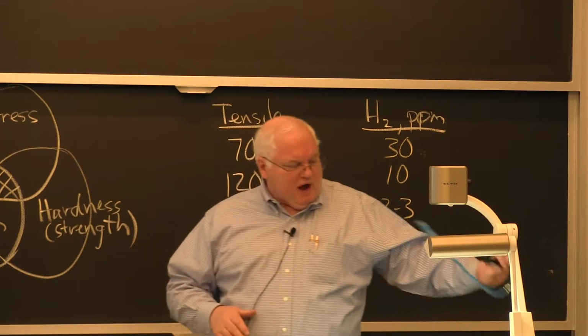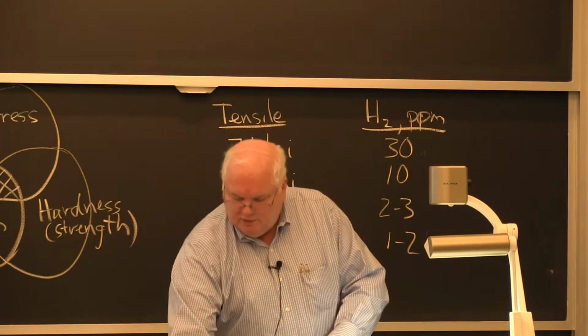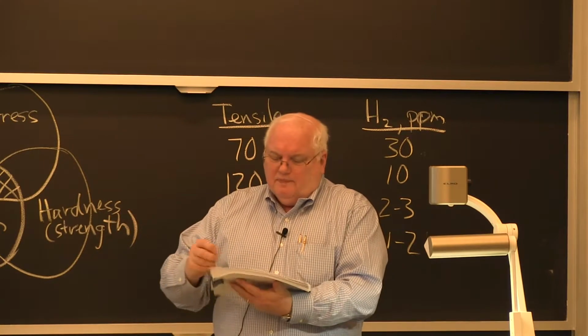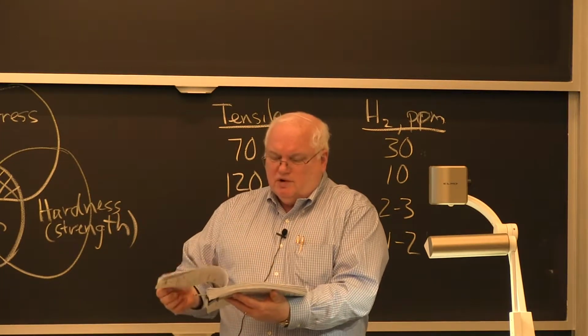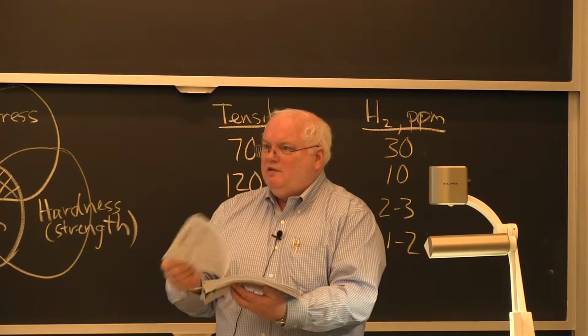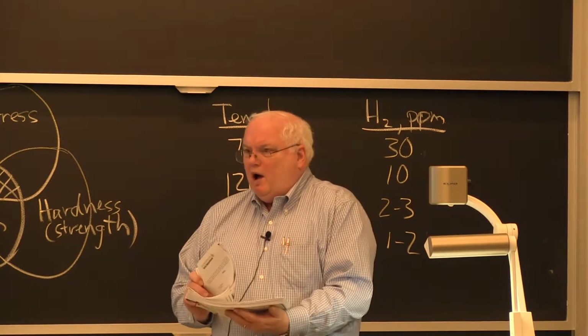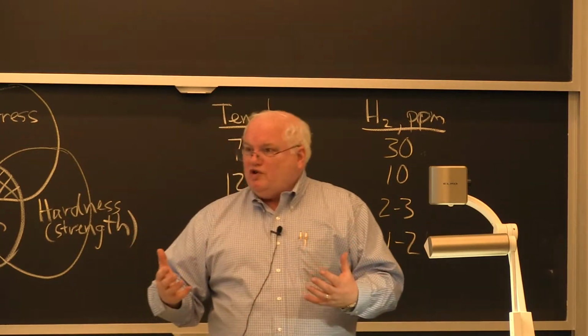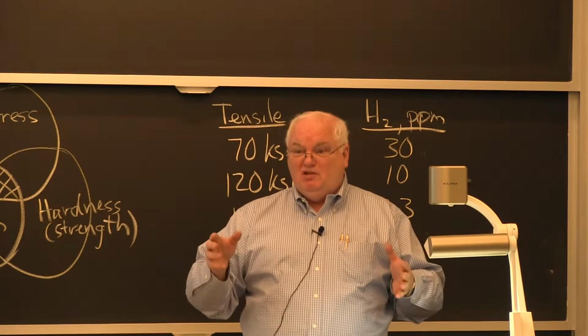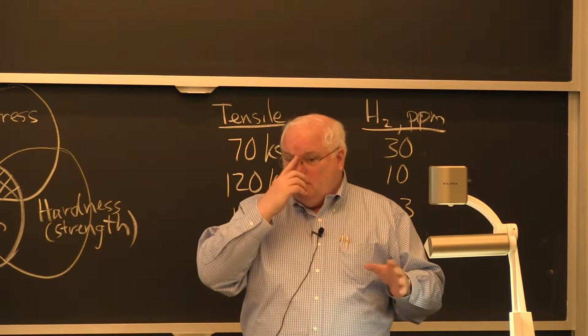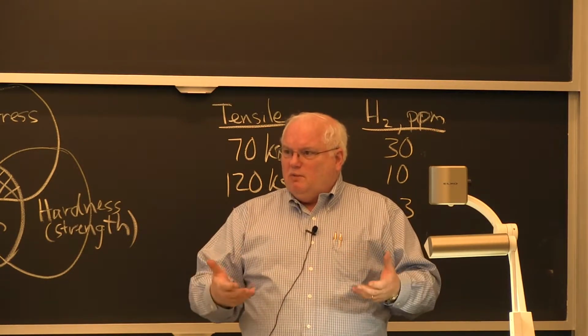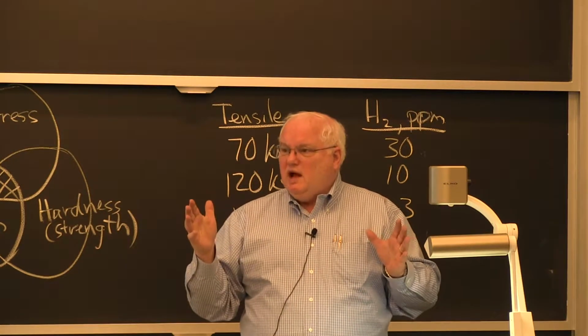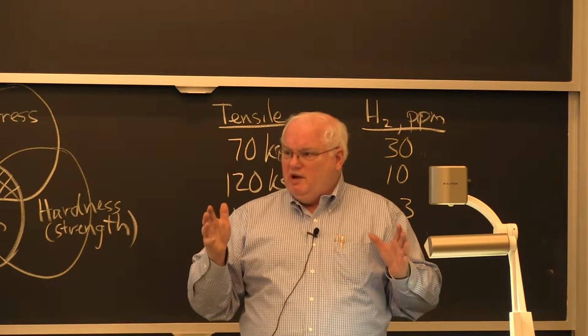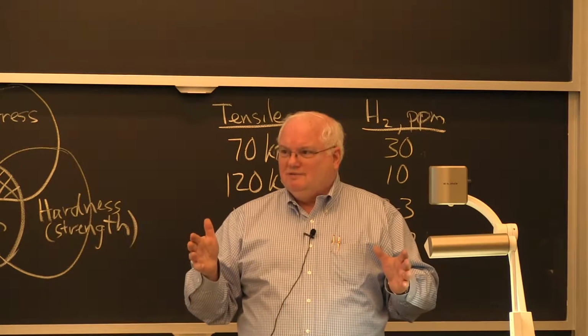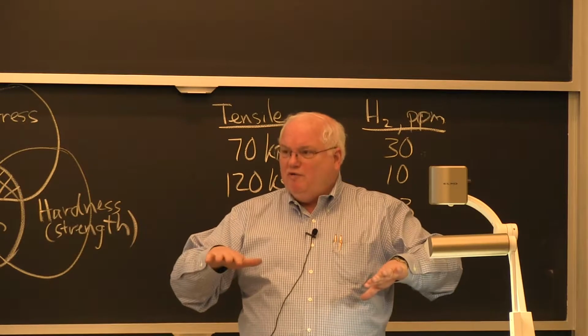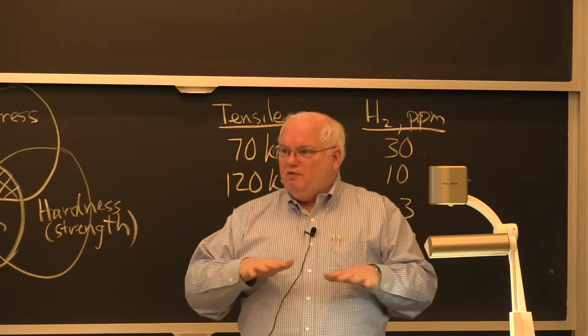Okay, and if I have a piece of steel, let me take this and say this is a piece of steel, and I machine away the top layer, if it's got residual stresses, it will warp because I took away the residual stresses here. It might warp down, it might warp up. But in fact, that type of distortion, if I take a heat-treated part, whether it's steel or aluminum that's been heat-treated, I start machining it, and it walks on me. It can move 10, 15 thousandths. I'm trying to do precision machining on a heat-treated metal part. I got problems, okay? It will move on me, and so you have to stress relieve the part before you're going to do some machining.